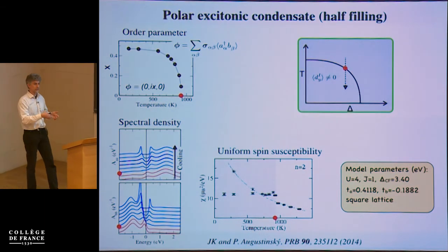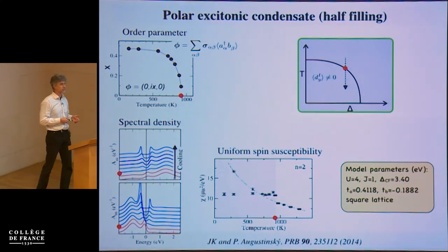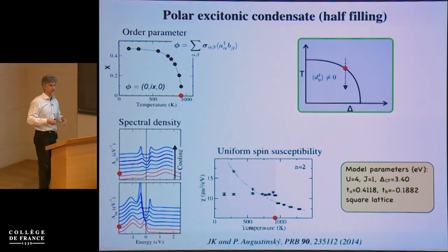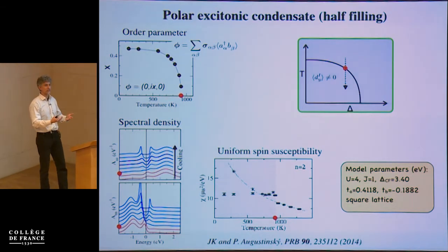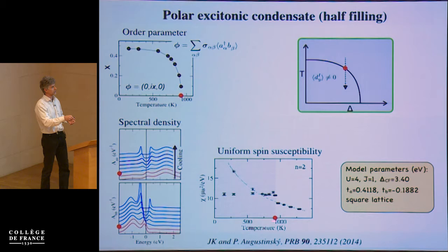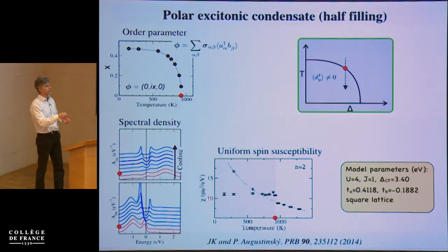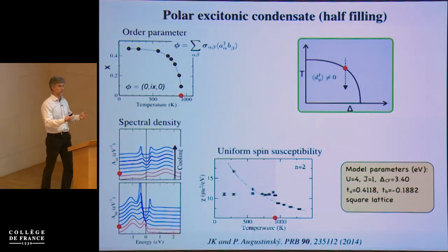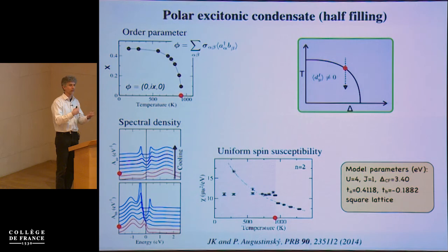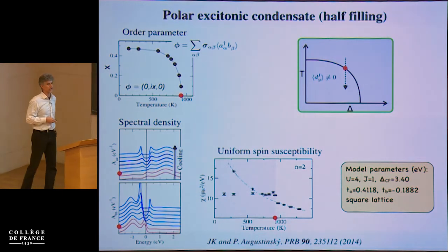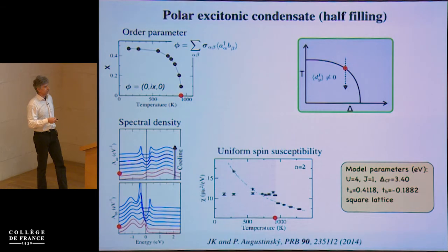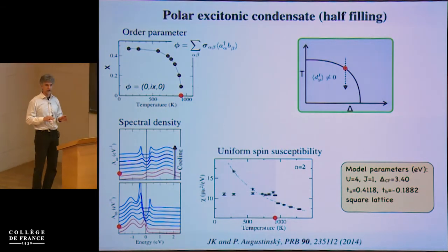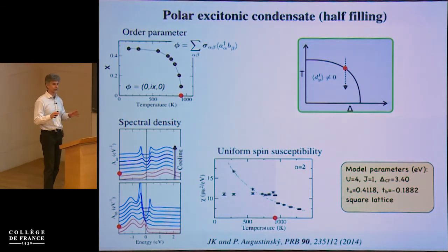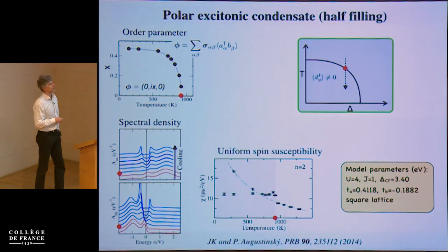As I explained before, this comes from the thermally excited high spin state. At the condensation, the high spin still remains in the system, so the susceptibility does not go to 0, but it remains temperature independent. So the high spins cannot now respond as free local moments to give you this 1 over T behavior. This is actually a quite simple explanation. If you're interested, you can ask at the end, but I'm not going to go into that now.